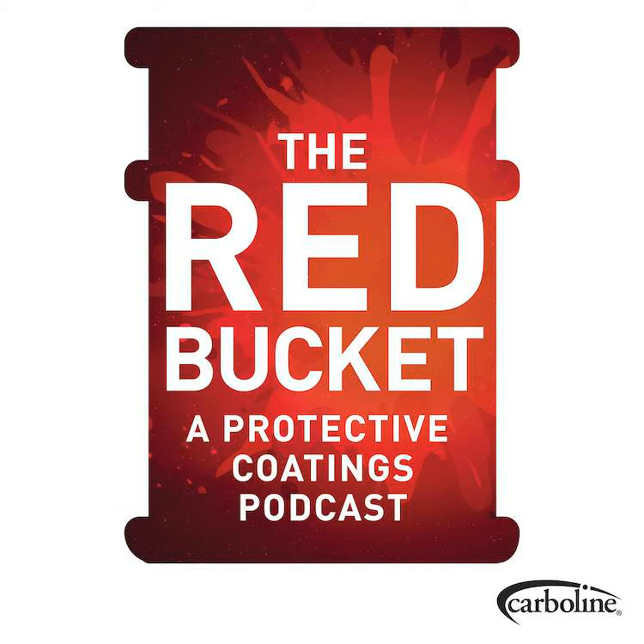And so, talking about those two features with regards to edge retention and flow and wetting characteristics, this product does actually seem to have both. It flows really nicely into the pits and into areas that need good wetting, as opposed to bridging over the top of those and leaving some sort of gap underneath. But yet it also holds the film thickness nicely on the sharp edge, so you get adequate coverage on that edge, but then you also adequately flow into those irregular areas and pits. So it's kind of unique in that regard.